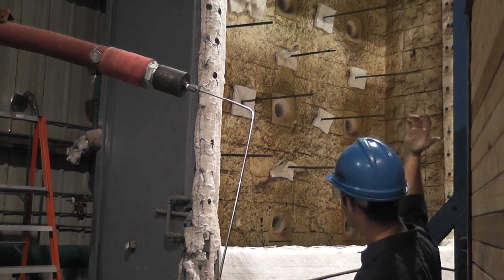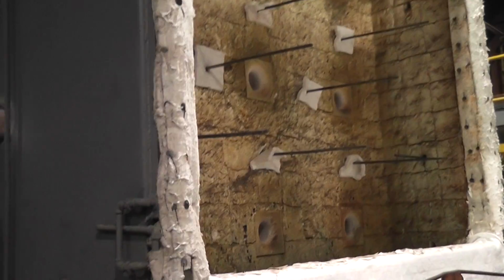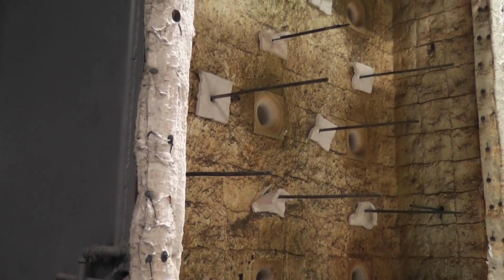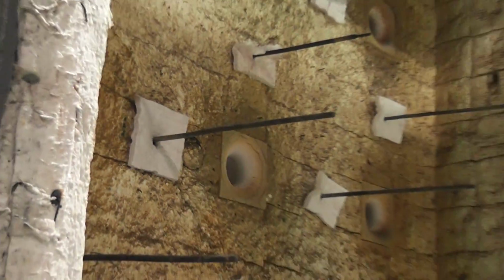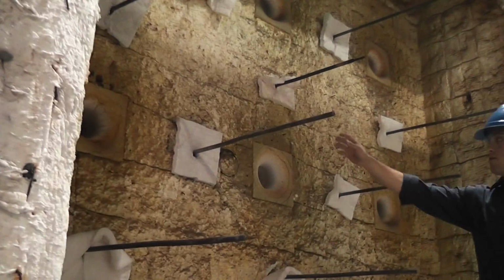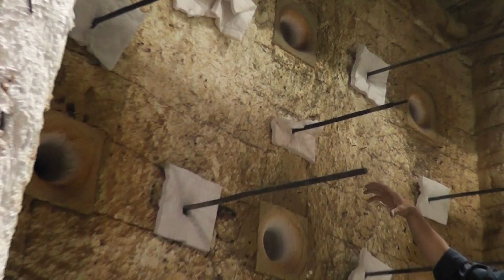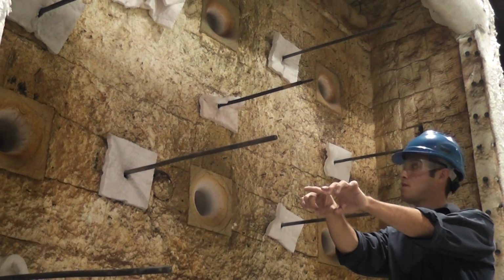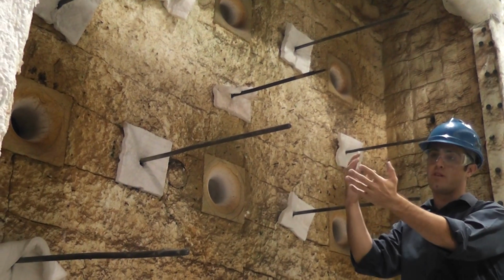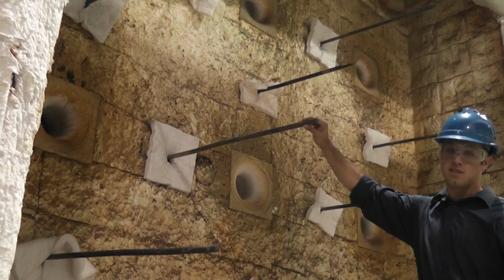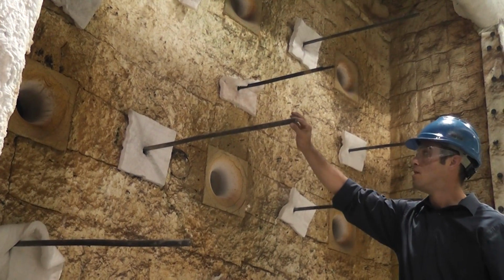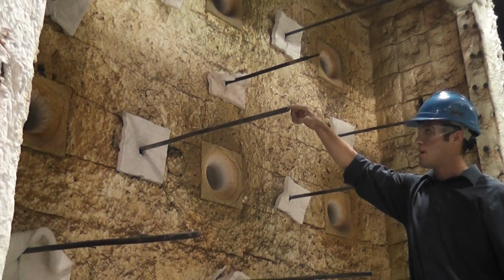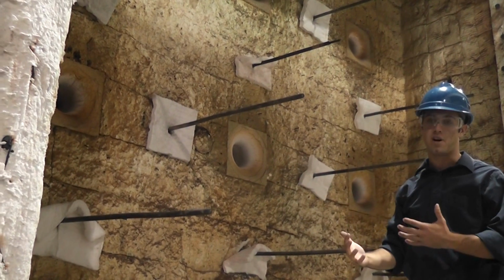The probes coming through the back face of the furnace are temperature sensors. The ones that are installed in there right now are for the ASTM E119 standard. I'm going to get up here and just point at a couple different ones real quick. So this is your standard E119 probe. It's a type K thermocouple. Inside this metal tube is a ceramic insert, a double bore ceramic insert. You have 2 different material wires that go through the 2 bores of the insert. They have a welded junction where the insert terminates, and then the whole assembly is placed inside an Inconel tube. Inconel is a nickel alloy metal. So your measuring junction is actually inside this metal tube, so it's shielded. So you get a slower response on these thermocouples.